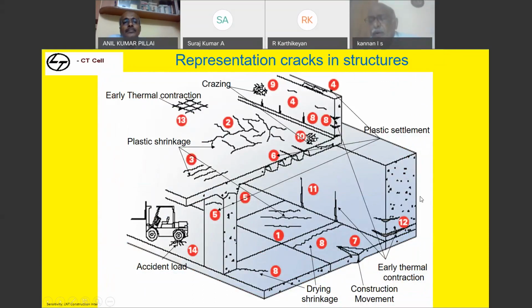Whenever you are able to see a crack on the slab, don't simply jump to a conclusion that it has happened only due to shrinkage. Anyhow, you can see in the initial phase by seeing the pattern and all. Every crack is not a shrinkage crack. Okay, so it needs to be analyzed by an expert who can understand the concrete phenomena. Then accordingly, the rectification methods also need to be derived, because the rectification method is not common for all types of cracks. Depending upon the cracking phenomena, the tendency, and the loading, what loads are applicable in the structure, the rectification methodology needs to be given, and the rectification process can happen.